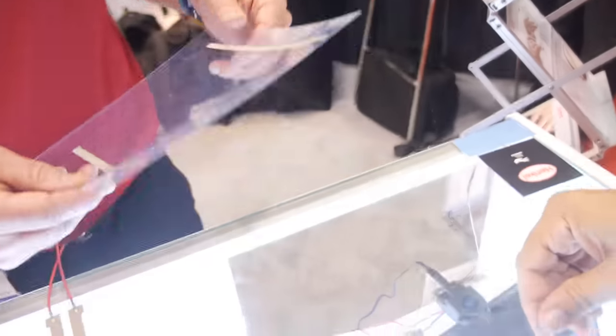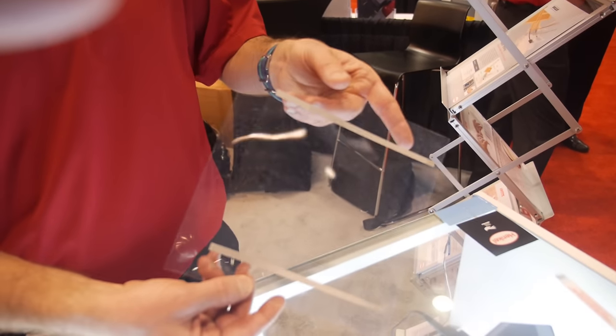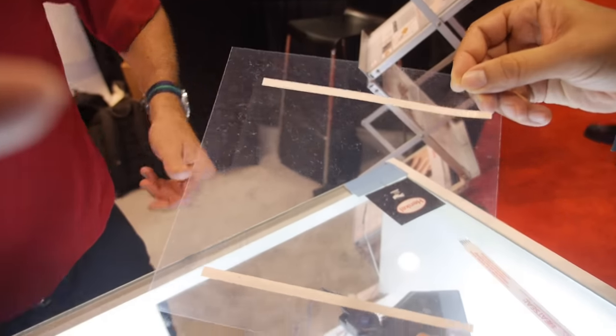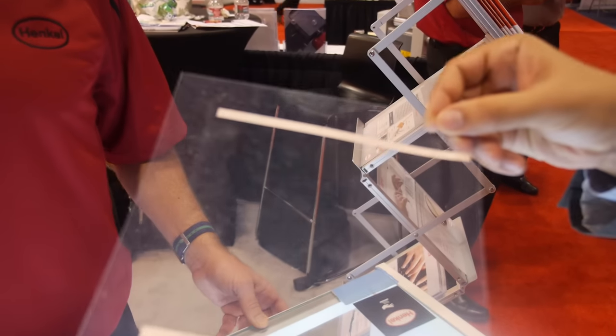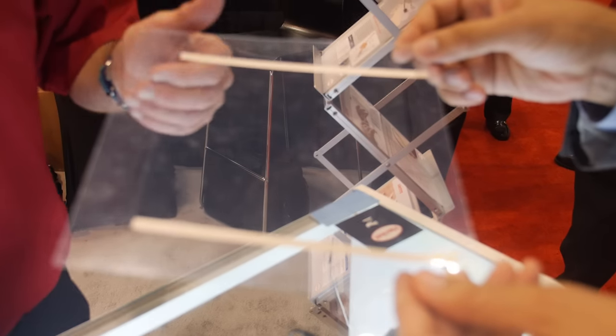The other technology that we have here is a transparent conductor designed as an ITO replacement. This is based on a silver nanowire technology — very difficult to shoot on camera because it's actually transparent. This material gives you a conductivity of about 90 ohms per square. So you've developed the silver nanowires? No, it's the actual composition with the silver nanowire coating.